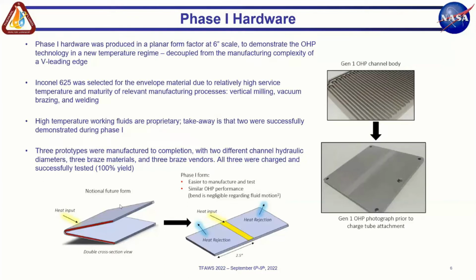You can see one here, and the heat map. The way they were actually tested, we took this notional future form of a leading edge geometry with a high flux input on the wedge. You transport the heat back and radiate off the adjacent surfaces, with some sort of near adiabatic internal surfaces in the wedge. And if you flatten that out, you basically get what we tested in phase one and in most of phase two as well, in terms of centerline heat input and then radiation and free convection in our test bed off the adjacent surfaces.